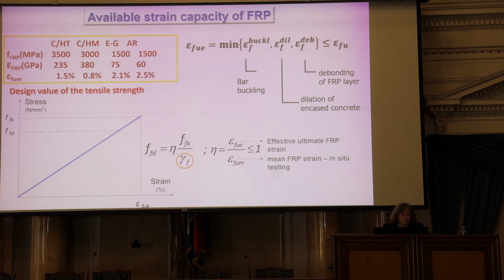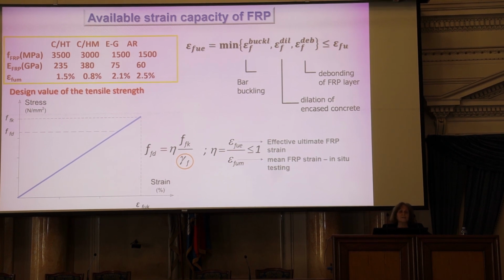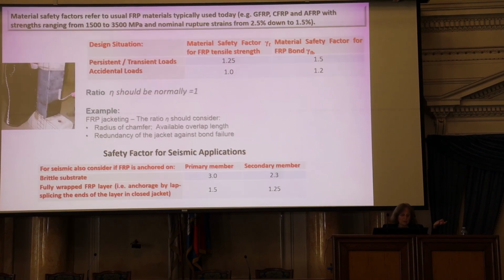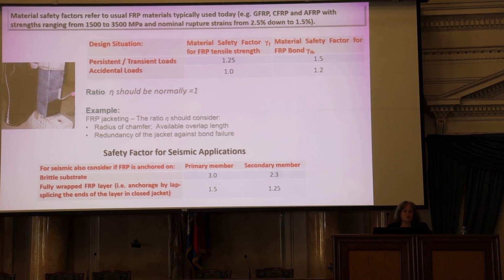So Bulletin 90 recommends that we use a design value for the FRP strength, which is obtained from the characteristic value divided by a material safety factor, and at the same time multiplied by a factor that accounts for local effects. For example, the top table gives you the material safety factors for different load conditions, for persistent and transient loads and for accidental loads, both for the material itself but also for its bond strength, whereas the lower table gives you the corresponding material safety factor for seismic applications. And as I said, there is another factor, eta, which is reducing the availability of strain capacity of the material, accounting for local effects, for instance, local rupture.